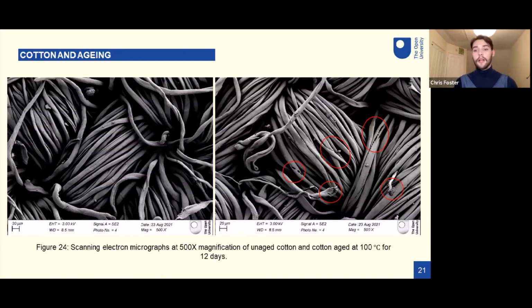So now looking at the physical implications this has, again, here's some electron micrographs. This is at a much lower magnification. On the left, you see the unaged cotton, and if you look closely at some of the individual fibres, you can see a twisting in the cotton fibre. There's also regions where there's a kind of twisting and a loop, and this is indicative of those weak points in the fibre, where the direction of the macrofibril spiral changes.